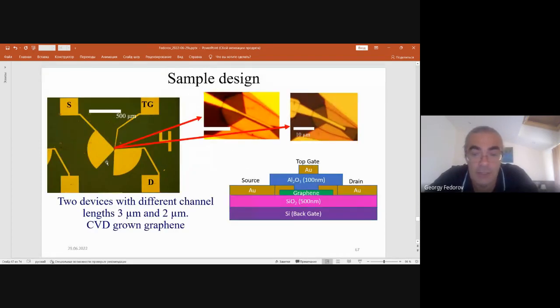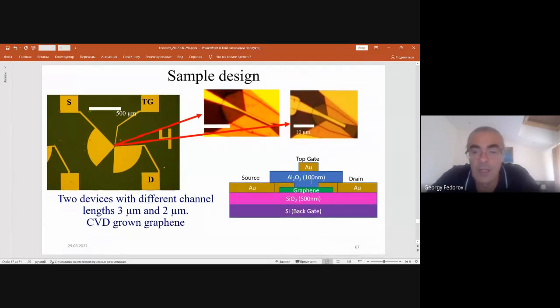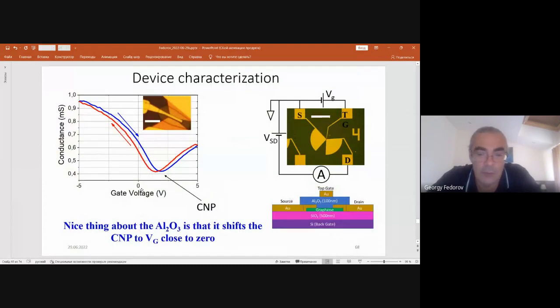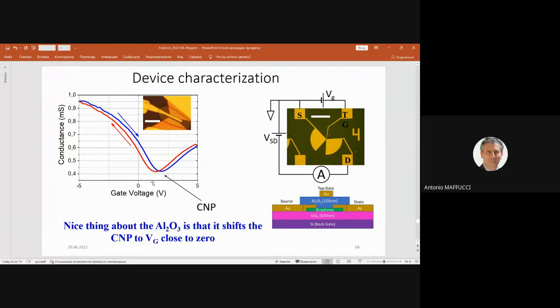So these are the devices that we made and probed. They have gates that are not as wide as the channel itself, just not to screen the effect of the radiation at the contacts. It was probably not an optimized structure, but still we see that aluminum oxide allows us to shift the CNP point close to zero.